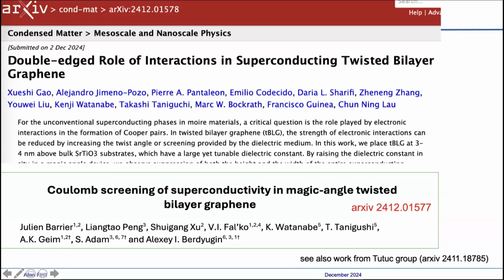Okay, so this work is now posted on the arXiv, and I also want to mention a work from the Bagugan group from Singapore, where they have put two twisted bilayer graphene on top of each other. One of them is almost like a Bernal bilayer. The other is magic angle twisted bilayer, where they can tune the Bernal bilayer in and out of the gap. They reach the same conclusion as us: if we increase the screening, that seems to suppress superconductivity in twisted bilayer graphene.